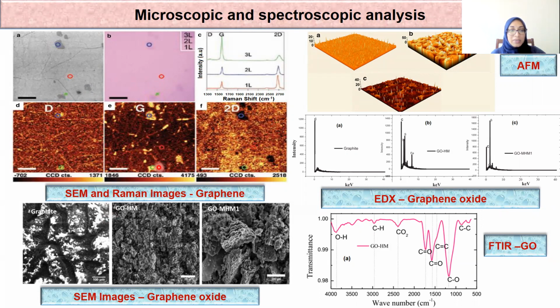The SEM pictures in this figure demonstrate that the thickness variation is more clear, and the existence of more than one layer in the flake is clearly visible on these maps. And all these indicate that the single layer, monolayer graphene was fabricated more than the other layers.